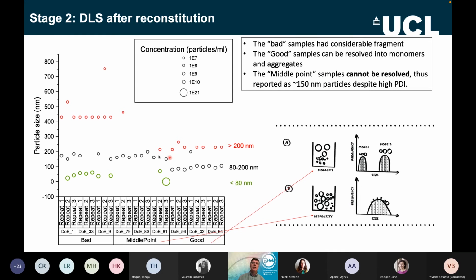If we look at that in a bit more detail, you can characterize the particle sizes more, because what I showed you before was the average particle size, but actually you can categorize them into different peaks that you can see and their populations. We can see the good formulations out here on the right are the ones where it's primarily in this range, 80 to 200 nanometers, which is about the size the particle should be, around 150. The middle point ones have mainly only that size observable, and then with the bad ones you start to get lots of very large particles and potentially some fragments showing up down here. So fragmentation might also be an issue in poor formulations.